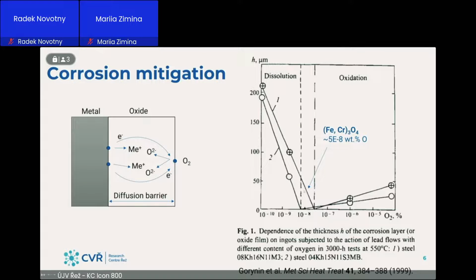It was demonstrated by Russians on their submarines that if you put a small amount of oxygen, 5 times 10 to the minus 8 weight percent of oxygen, you will develop this spinel, iron chromium based, that significantly slows down the corrosion process.